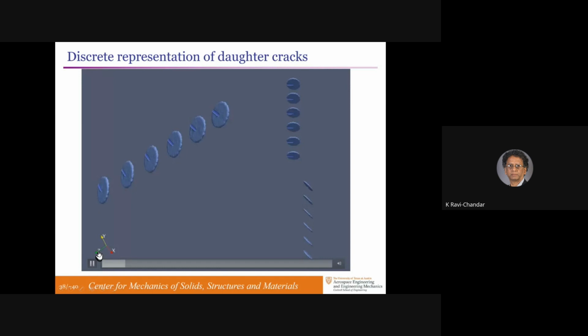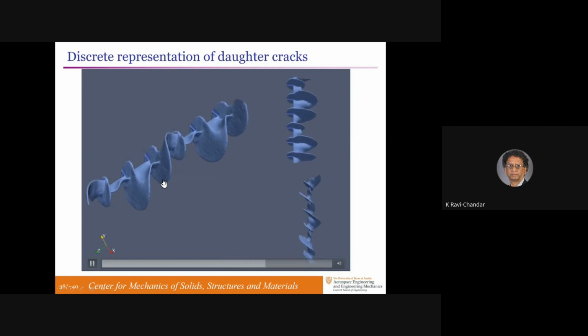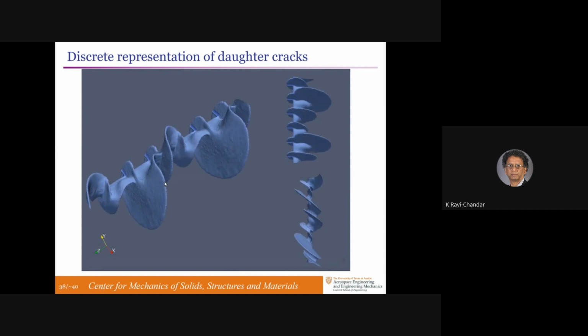So this is at a particular tilt angle corresponding to whatever the ratio of K3 to K1 needs to be for that. The parent cracks start linking up, they grow. The daughter cracks grow and shield each other. Here is the coarsening. This one and this one grew, the ones between them stopped. And so we've been able to reproduce fairly every feature of the experiment that we were able to see with the phase field method. The only thing is you need defects to start triggering this.